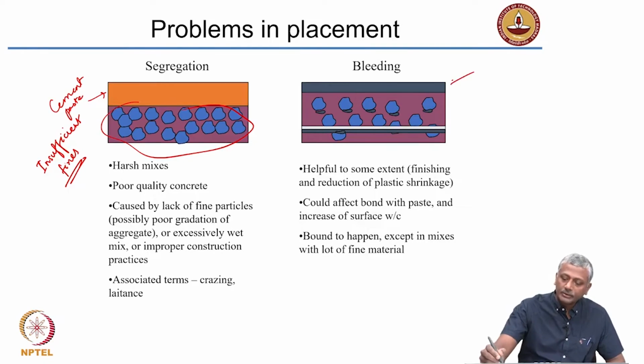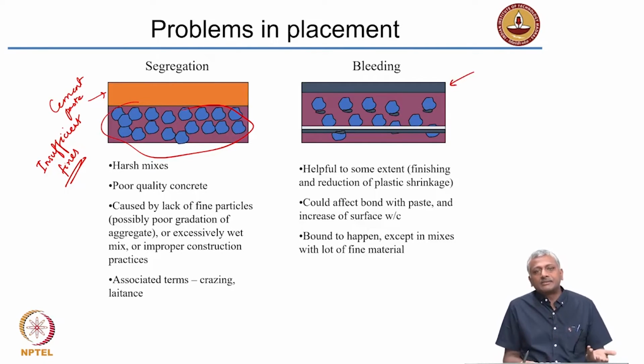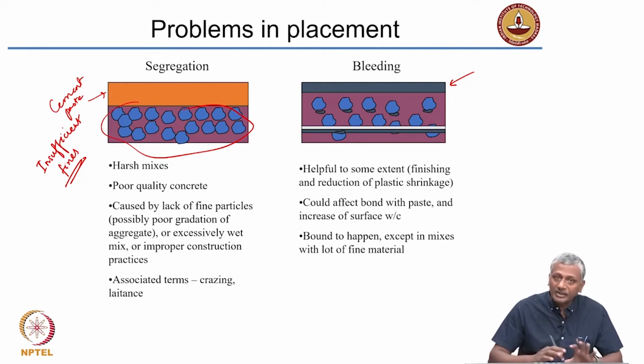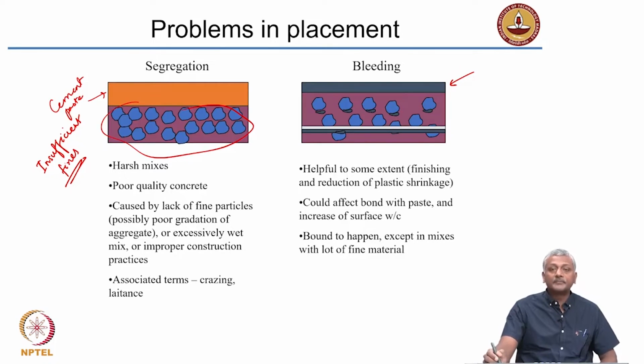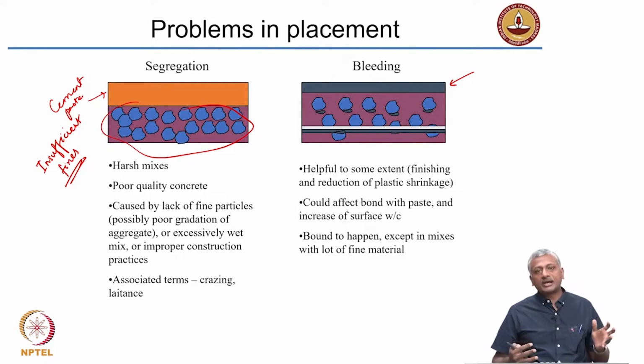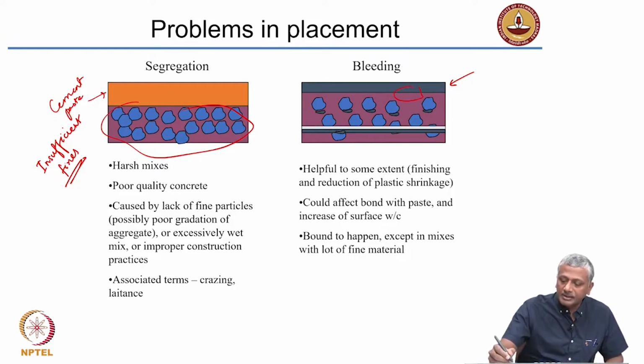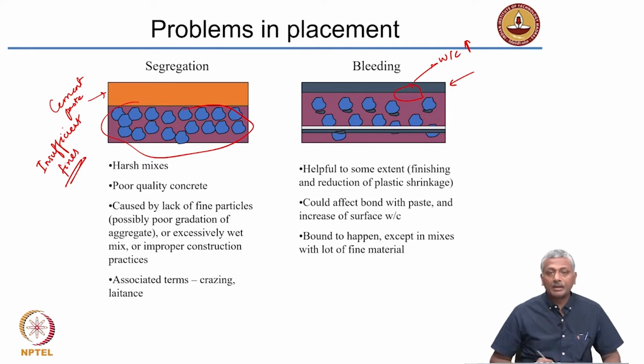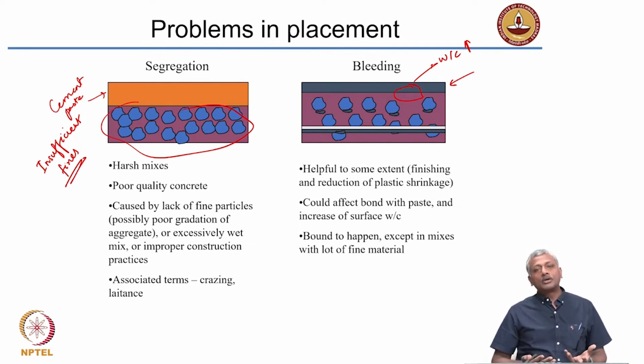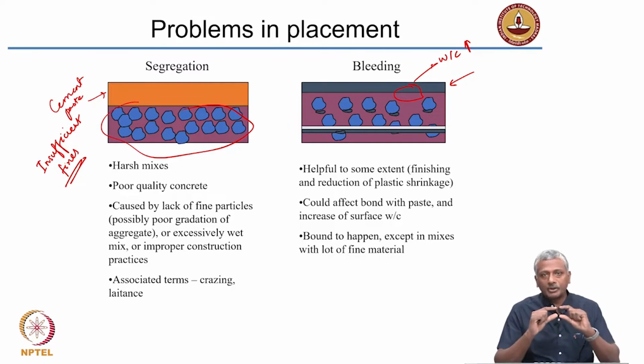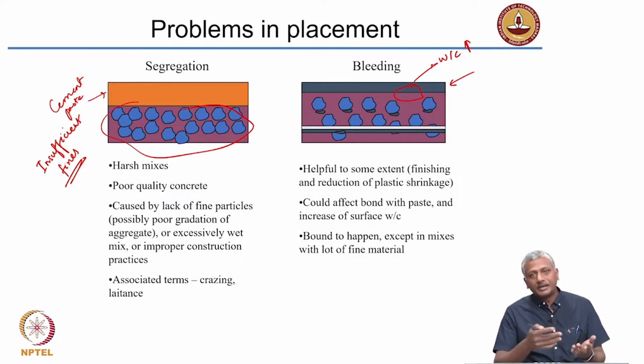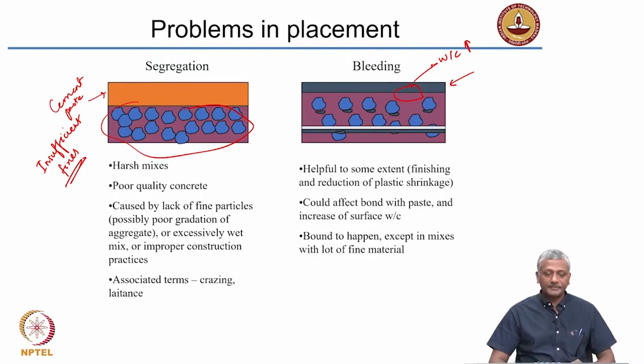If you have too much water, you will cause what is called bleeding. This water basically is the lightest ingredient of the concrete. So because of gravity, the water rises to the surface and forms a layer on the surface. That's basically called bleeding. Now while this bleed water on the surface helps to some extent in finishing and reduction of any shrinkage cracking on the surface, the problem is it's going to locally increase the water to cement ratio. Because more water is there, less cement is there. So the water to cement ratio of the local zone at the top of the concrete slabs will be higher, and if you have a higher water cement ratio, you automatically get a lower strength. Okay, so this is not a desirable situation. You don't want segregation and bleeding to happen on the site.